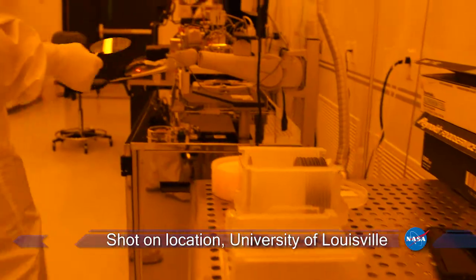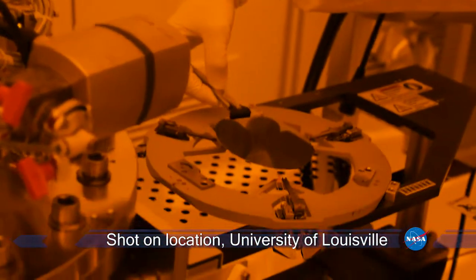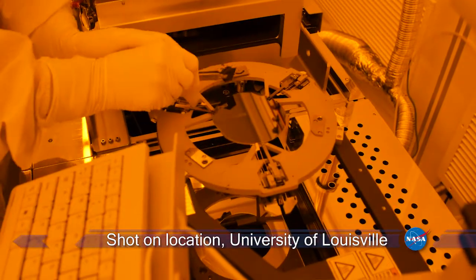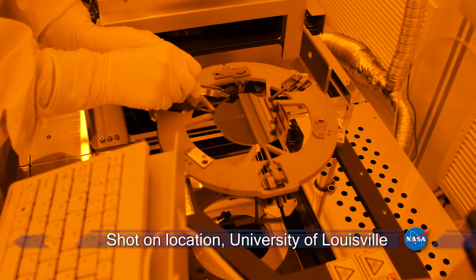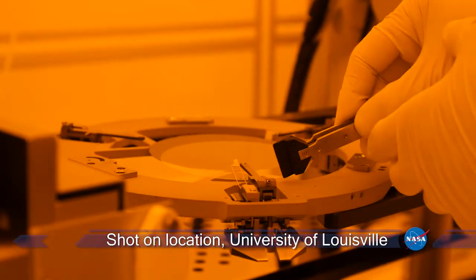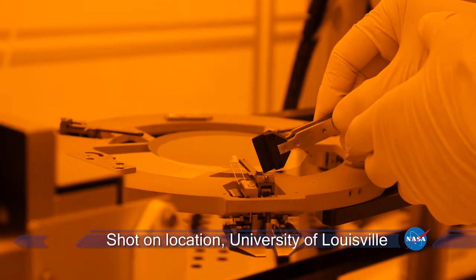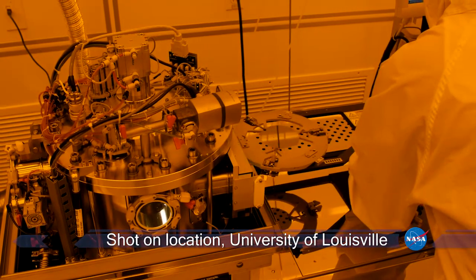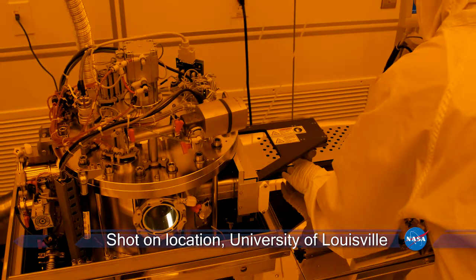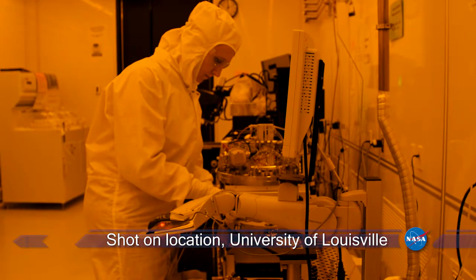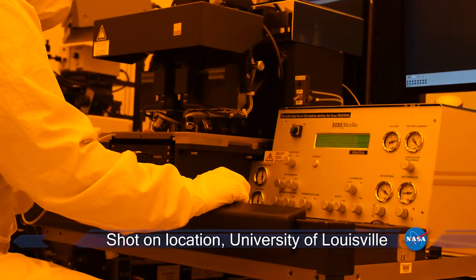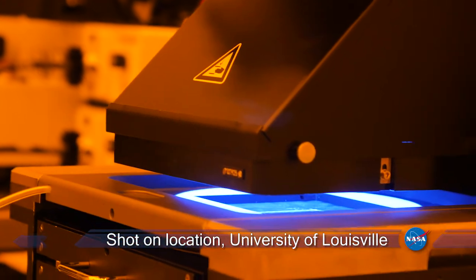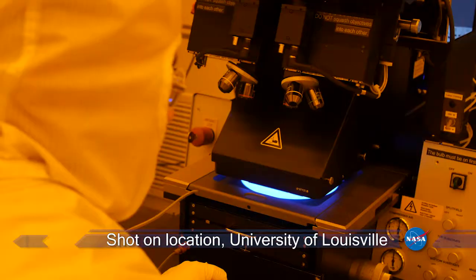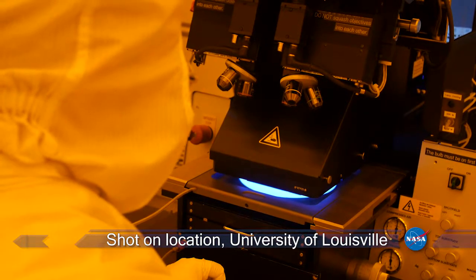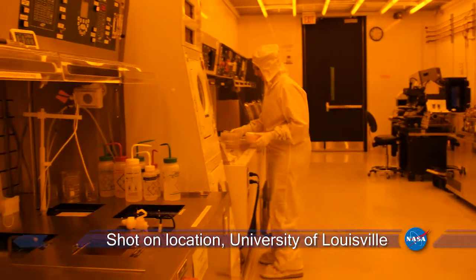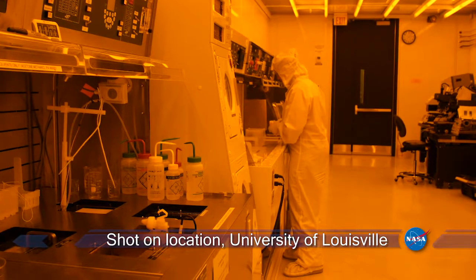At this moment, we're not sending up the true quantum dot sensitized solar cell system, partially because it's a little bit more difficult to generate. So what we're starting with is sort of an analog system where we're using a large particle that is very like silica and a smaller particle which is readily available in zirconia. These particles are very easy to modify, they're very easy to deal with in solution phases. We don't need to go to high pHs or very low pHs. They're very easy to suspend within an aqueous system. And so this allows us to really look at the fundamentals of nanoparticle haloing and how that crystallization can occur, so then we can transfer that knowledge to the actual quantum dot-based systems.